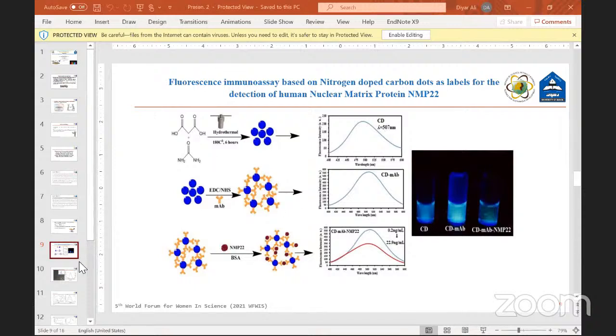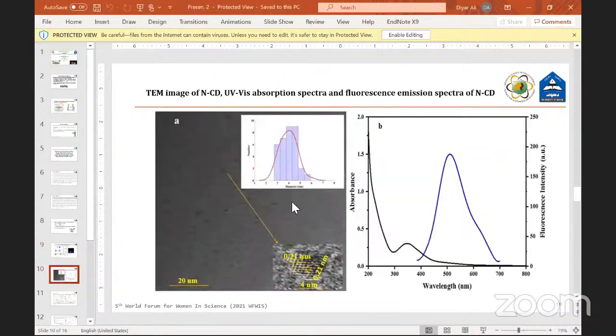Next, we did characterization of the nanoparticle. We did HRTEM and TEM. With the HRTEM, we can see the size of our nanoparticle is 4 nanometers, and the size distribution shows that most of the nanoparticles synthesized by our method have 4 nanometers in diameter. We also took the absorbance and fluorescence of our nanoparticle, which ensures that we have nanoparticles: we have 2 different peaks in UV-visible, and also the emission peak at 500 for fluorescence.